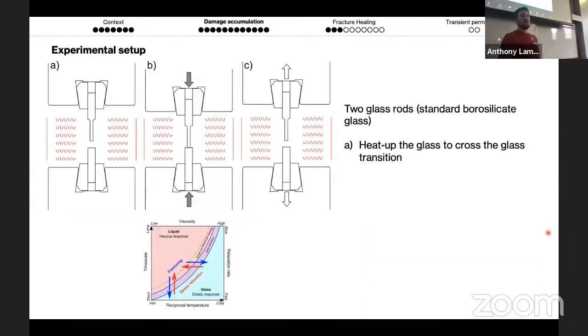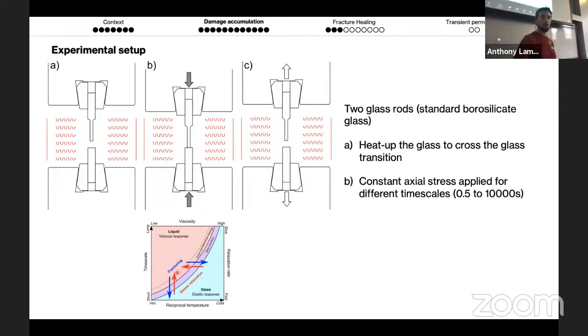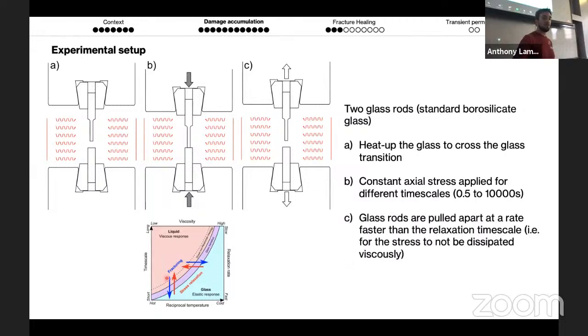So the experiment setup is that I have glass rods that are put into a furnace and heated above the glass transition temperature. So I'm going to be in that red regime here. And then I'm going to apply a constant stress for a long time. And then I'm going to pull apart to fracture the glass. So to cross the glass transition, I'm basically going to be going through that cycle over and over again.